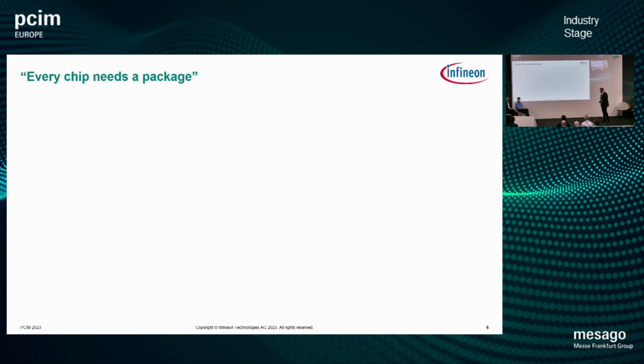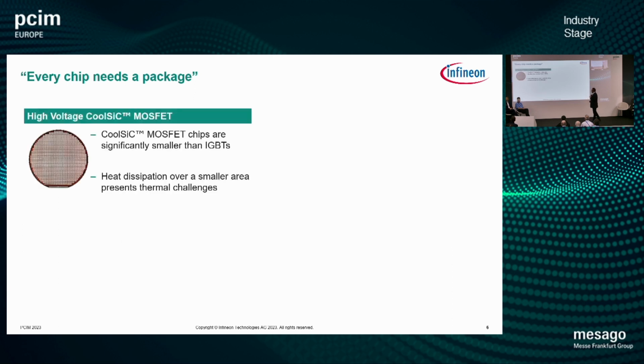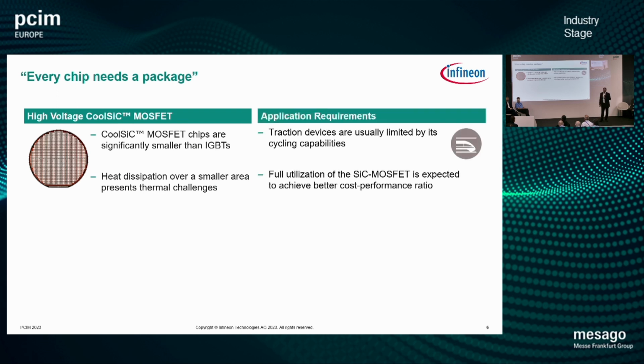Of course, many can make a very good chip, but every chip needs a package, and it's very important to properly house it. One of the challenges with silicon carbide MOSFETs is that they are very small in size, so you have to dissipate a large amount of heat over a very small area. When you focus on applications like traction, which most of my colleagues also mentioned here, there is a very high cycling requirement in terms of load. This means you have a very small chip with a higher RTH value, and at the same time it needs to fulfill the traction requirements and the cycling capability.